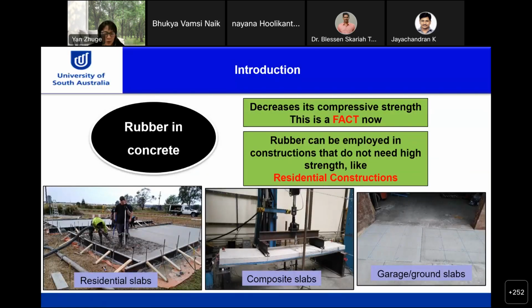Through 10 years of research, we have gained a pretty good understanding of the crumb rubber concrete, or CRC, performance. For example, we know the compressive strength will decrease as you increase the percentage of rubber. Everyone knows about these results. When you use rubber up to about 30 or 40%, there is a sharp drop of compressive strength.